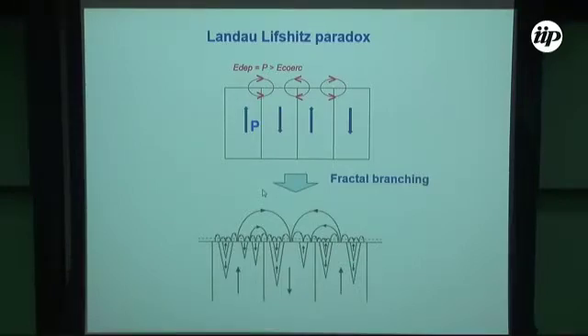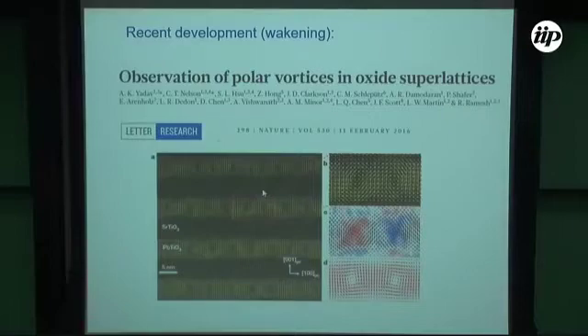And finally, they discovered that the field, which does not penetrate into the bulk, is still very, very high at the surface. It's higher than the coercive field. And because of this, they said that in principle, close to the surface, the polarization should reverse its direction. And then, if you consider a smaller scale, it should reverse again, again, again. So in principle, in the ideal system with infinitely thin domain walls, we should have so-called fractal branching of domains. There were even several claims of observation in magnetic systems. I think in superconductors, they really observe such type of branching.